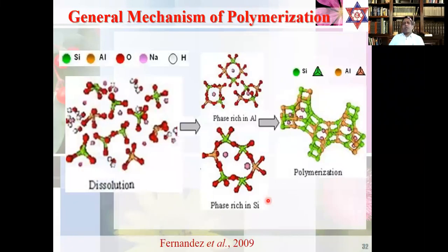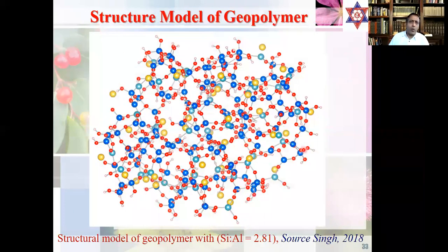So this is the mechanism of geopolymerization. First, it starts when you treat with alkali, hydroxide dissolution starts, then an aluminum-rich phase and a silicon-rich phase will be produced after dissolution. Again, polymerization occurs and you will get the polymerization of aluminosilicate materials with alkali metals in the network, and this is geopolymer. So this is one structure model of geopolymer materials.